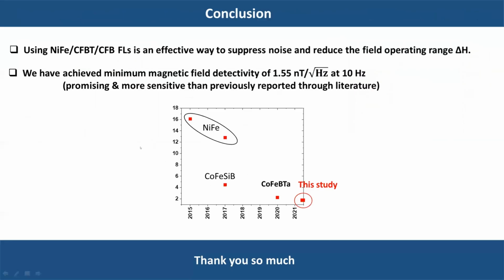So in conclusion, we have achieved a minimum magnetic field detectivity of around 1.5 nanotesla per root hertz at 10 hertz, which is promising and more sensitive than previously reported in the literature. So thank you so much for listening and attending my presentation.